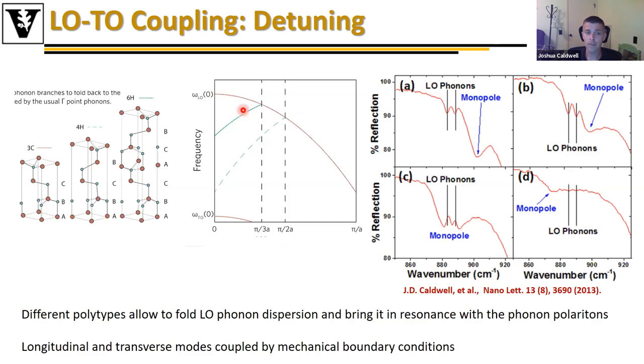2013, we use 6H, and this folds over at a third of the Brillouin zone, resulting in modes at about 882 wave numbers. And there's actually two of these that are nominally degenerate, but split a little bit here for a variety of reasons that I can get into otherwise.